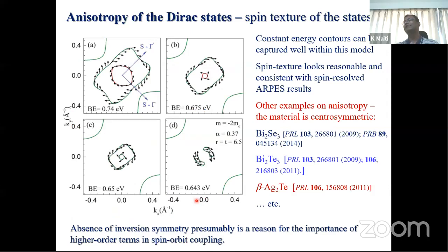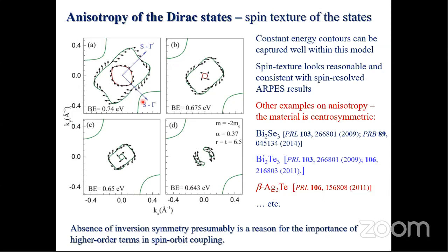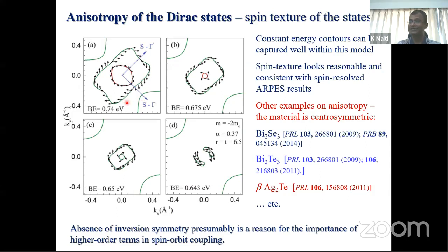So basically, you can also plot the spin texture using that Hamiltonian that I have shown. So what we try to say is that actually this is an extremely interesting material where you see that the absence of inversion symmetry probably is giving you additional complexity in your spin orbit coupling. So probably this orbital moment is higher, and higher order spin orbit terms become important for this kind of material.